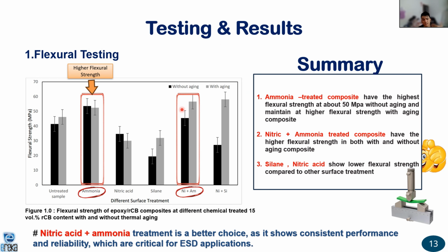First of all, I will explain the flexural testing. We can see that when we use the ammonia, it can show the higher flexural strength at about 50 MPa without aging and also after aging. The dual surface treatment can also show this, but the nitric acid plus ammonia treatment can show the higher flexural strength in both the with-aging and without-aging composite.